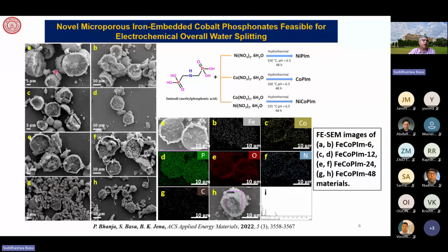And the results of the SEM structure at different hours of refluxing: A and B is 6 hours, C and D is about 12 hours, E and F is about 24 hours, and G and H is about 48 hours. So you can see a sort of core-shell structure, and that has been broken. So it's kind of a half core-shell structure. It's not a complete sphere. It's kind of a half sphere. You can see nicely here that you get a half sphere.